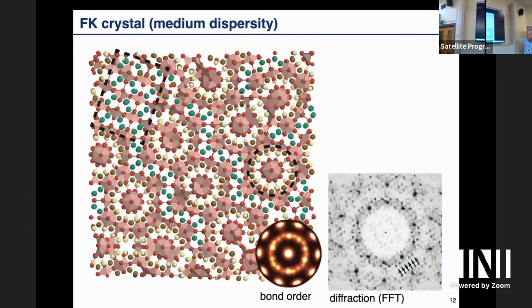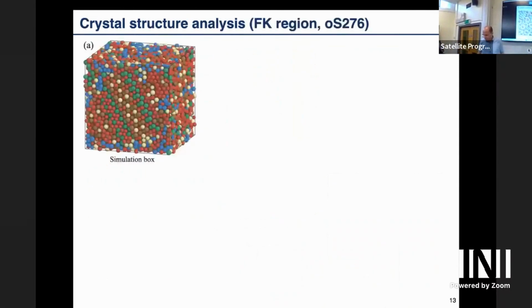And here is a cut through the sample. We make the particles a bit smaller so you can see inside. And you see it's a very complicated structure. So you have these ring-like clusters and you have these green ones. And this is again the bond order diagram, now averaged and a bit nicer. This is a diffraction pattern. So there are apparently some very complicated structures you can crystallize when you follow these systems.